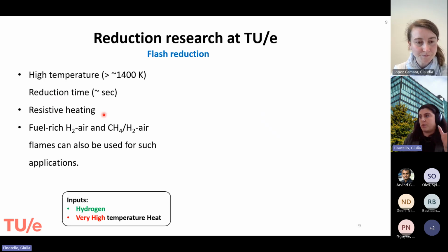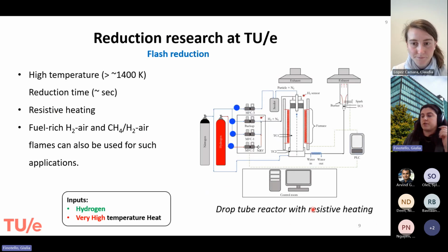Indeed, we are developing a drop tube reactor where we have resistive heating, and we want to do very controlled experiments to look into the kinetics of a reduction at such high temperatures, which are still very much unexplored. And potentially you can also do it with a hydrogen-air and methane-air hydrogen flame to reduce that. And what you need are, of course, hydrogen again and very high temperature heat.